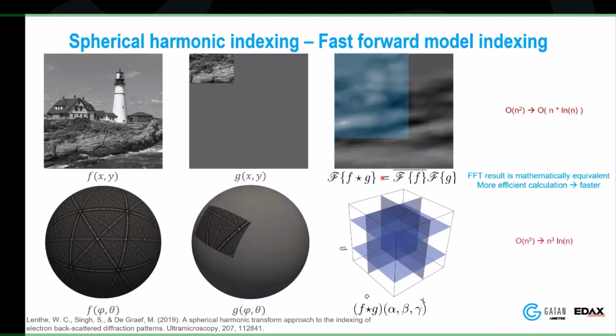Now, if there are any math nerds out there who really fully understand this stuff, there's a good paper out here by Will Lenthe and Mark DeGraff and this gentleman here that was published not too long ago, back in 2019. We call this the spherical harmonic transform approach. And this is where the spherical indexing comes from, this math. It's just a fancy mathematical term. So you're basically taking your little projection of your phosphor screen here and going backwards to get what you need. Now, mathematically, this is much faster. So this is why we do this, because it's more robust and it's faster when we're doing things post-processing wise.